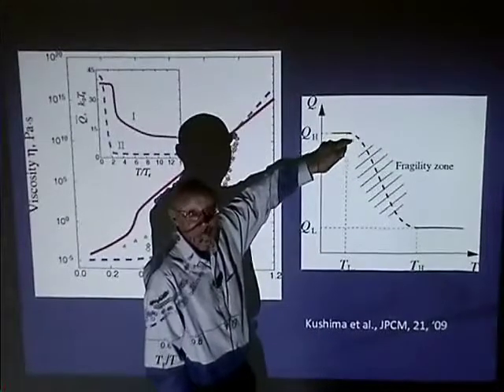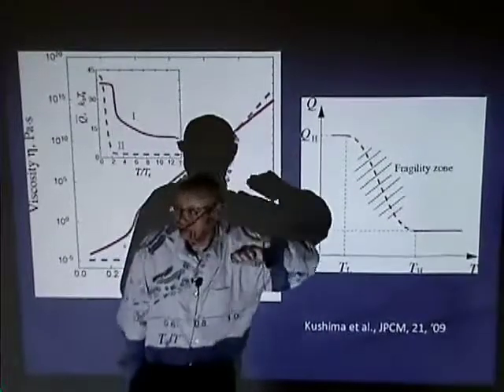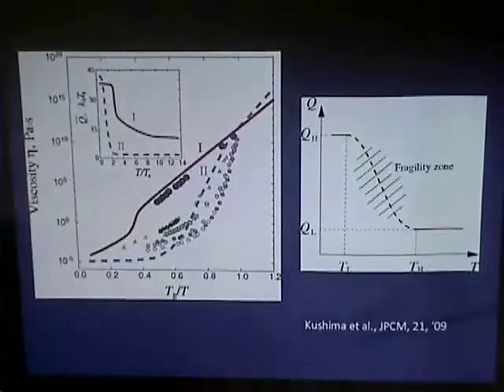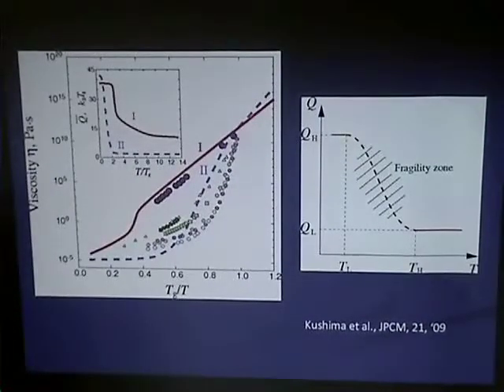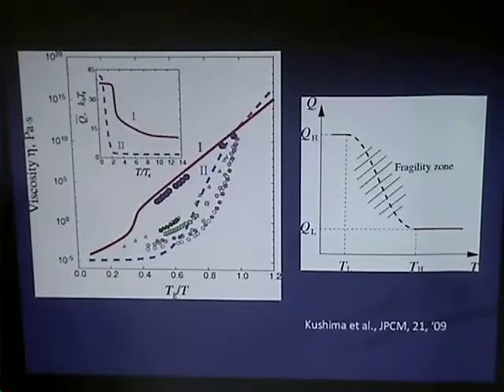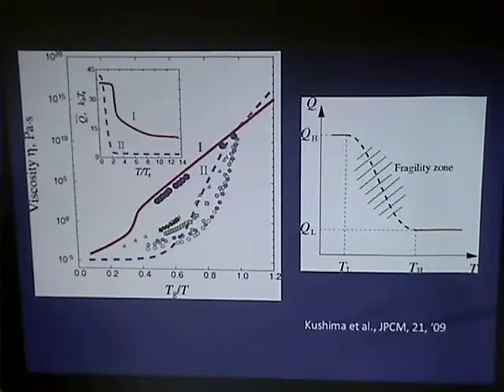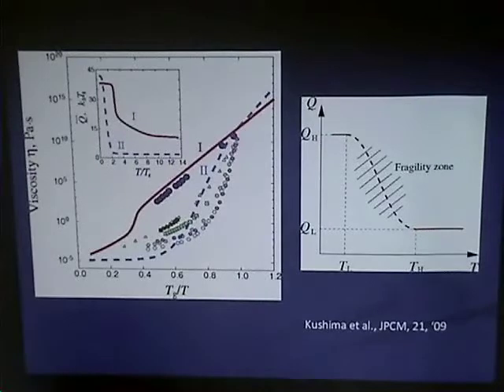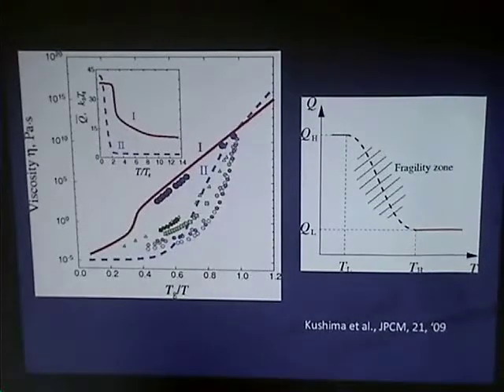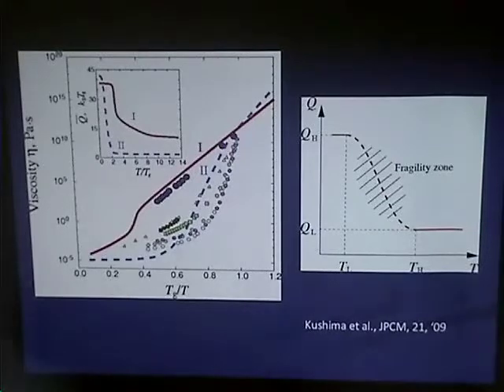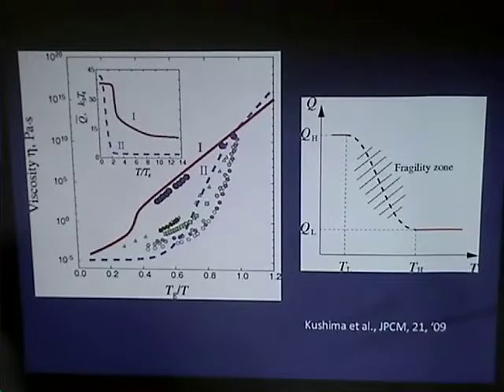Yeah, for example, in confined water. My point here is actually when you compare to the distribution of the temperature in the landscape versus temperature, that is a much broader temperature range than the transition, at least in the metallic glasses these people see. So it's around what you see here in your blue curve, about 0.2 of Tg, you see a transition in the activation energy. That's a very narrow range. It is very sharp. Very sharp. Exactly.